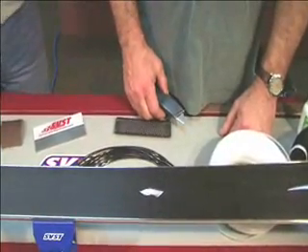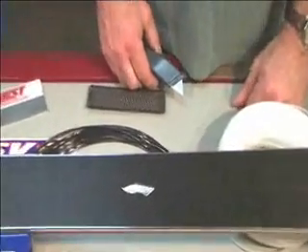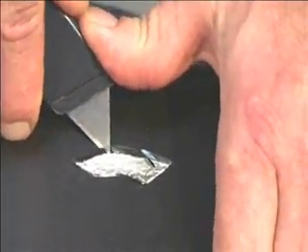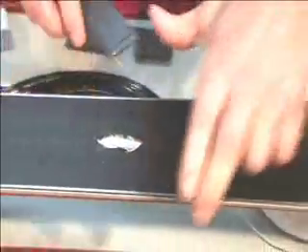Okay, so where we're at now, we've got a repair here, a base core shot that we cut into the ski, and what Ed has done is gone around the perimeter of the repair with a razor knife, cutting at about a 45-degree angle. Once we get this trimmed out, we will work it over with some 120 grit aluminum oxide shop roll paper to rough it up so we get a little better adhesion when we put the beads of weld down.